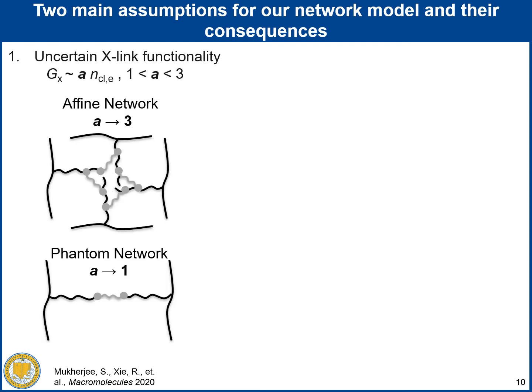To address this issue, we decided to build our own model by making the two main assumptions below. First, because the crosslink functionality is uncertain, we introduced the proportionality constant A to relate the network moduli to the number of elastically effective crosslinkers between the two ideal limits, namely the affine network and the phantom network limits.